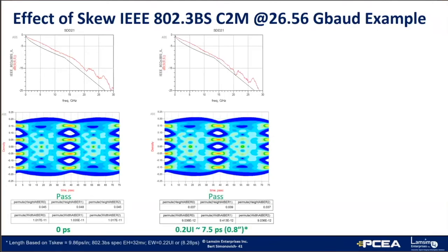When we add 0.2 UI of skew, or 7.5 picoseconds, we see the insertion loss being pulled closer to the insertion loss mask. This is due to the resonant notch we saw in the previous slide. We can't see the notch because it's beyond the bandwidth of the measurement. But in this example, the eye height and width are reduced, but they're still within spec.